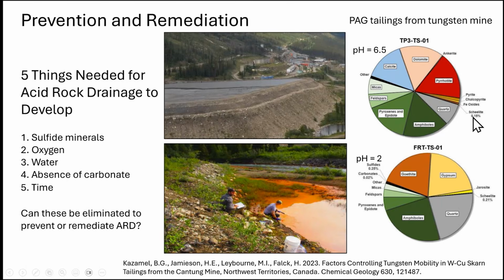So you have scheelite, the ore mineral. Of course, it's still there in the tailings, not too much of it. But you have carbonates, you have both calcite and dolomite, and you have a sulfide, you have pyrrhotite. And you can't tell by just looking at the pie chart whether you've got enough calcite to take care of that pyrrhotite if it oxidizes or not, or enough calcite plus dolomite. It's a more complicated calculation. And then on the other side, you have a bunch of silicates, which honestly don't play as big a role.